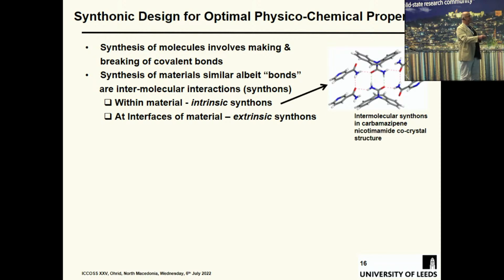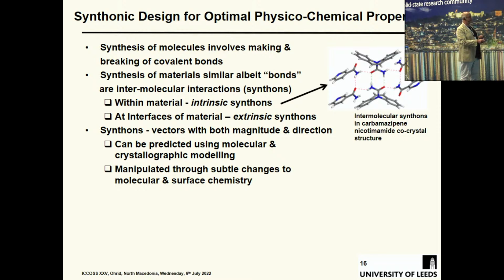So you take this lovely co-crystal of carbamazepine nicotinamide, we can see all these synthonic interactions between the molecules. And it's worth remembering that the interactions are interactions between all the atoms in the interacting molecules. Our eyes go to the hydrogen bond because we say the hydrogen bond is the strongest, but it's only the strongest per atom. It's not necessarily the strongest per molecule. And that's a huge factor when the molecular weight goes up. When these are at the interfaces of the material, we call them extrinsic synthons, and the extrinsic synthons are important. Synthons, of course, from an engineering perspective, are vectors. They have both magnitude and direction that is driven by the crystallography, which is why the crystallography is important. And you can predict them with molecular and crystallographic modeling, and you can manipulate them through subtle changes in both the molecular chemistry and the surface chemistry of the material.